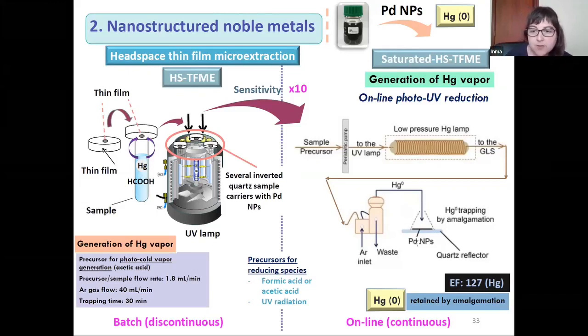Here, the enrichment factor obtained for mercury was 127, less than in the previous publications using hydride generation. However, this has the advantage of not using sodium borohydride, which has different problems, such as the high amount of hydrogen generated, the residues generated also, and the instability of the sodium borohydride solution that needs to be stabilized with sodium hydroxide.